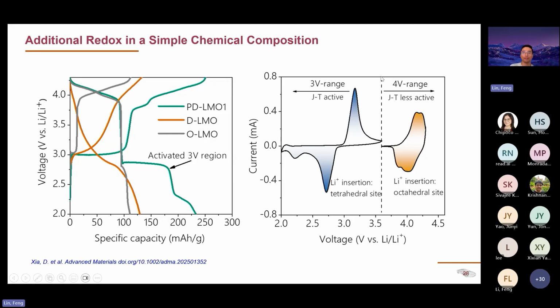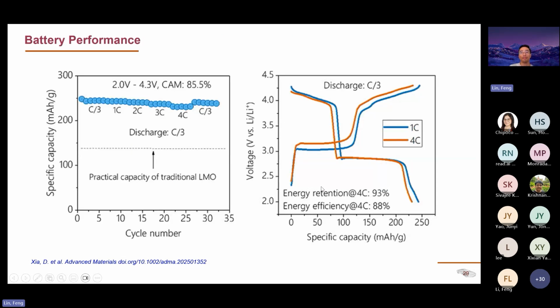And from this CV test, you can also observe the two different redox processes, high voltage redox process and low voltage redox process. This material can perform at very fast rate. So the energy retention at 4C is 93% compared to a 1C rate. This is charging at a high C rate and discharging at C over 3. We don't see a lot of energy penalty between the 1C and 4C.